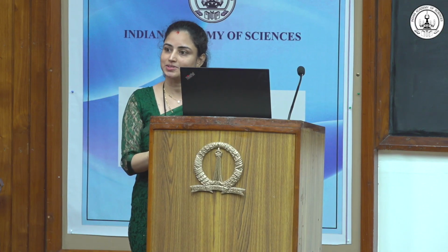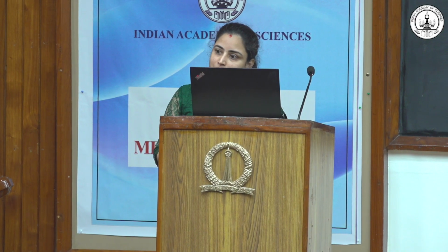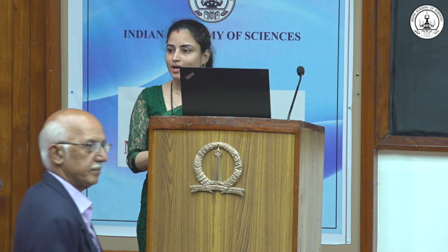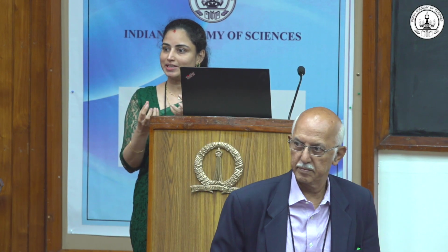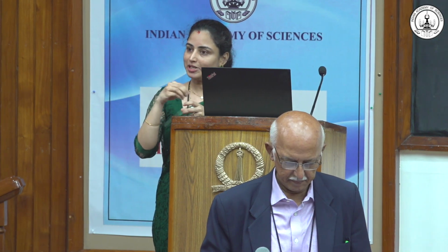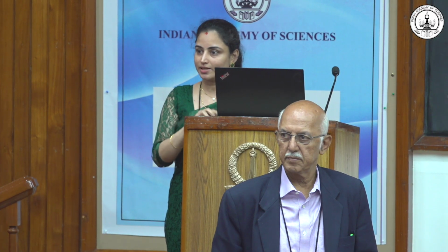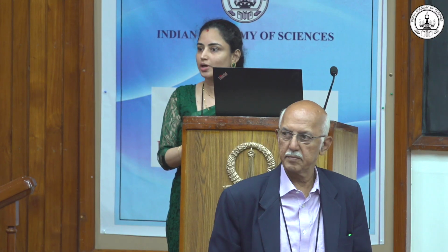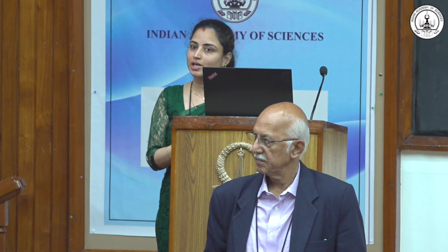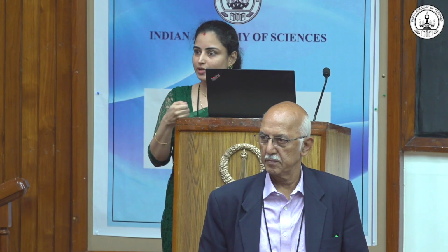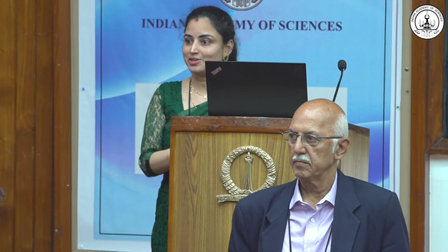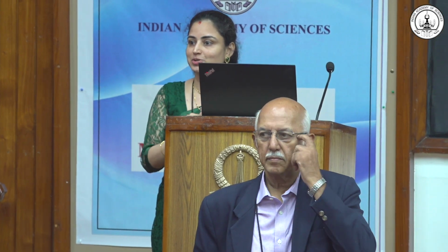Excellent science. Thank you, sir. How do you prepare the material, particularly the one with the tungsten? There are high melting materials. It's sealed tube reactions. We take the starting materials, add them into a quartz tube and then heat it to a very high temperature in a vacuum. By what? Induction melting, arc melting, or what is it? No sir, for some of the things it's normal melting, like in the oven we reach up to 1200 Kelvin or so, and in some cases like SHS, we directly use a flame torch to heat the samples. No, tungsten being high melting? Tungsten we haven't synthesized yet sir, we have just calculated the electronic structure and it is yet to be synthesized. Okay, thank you.